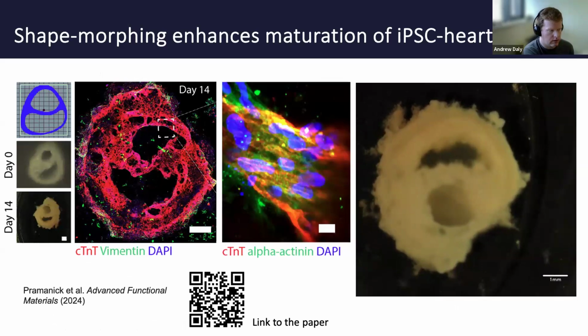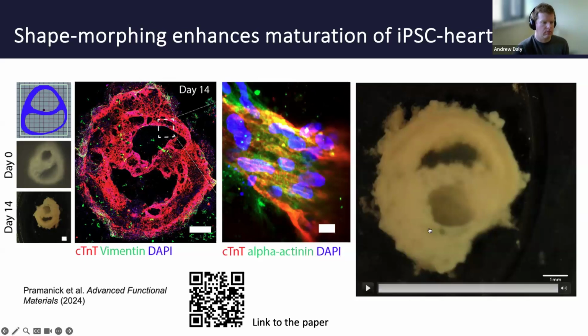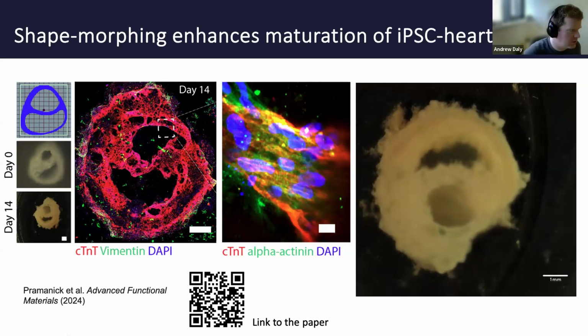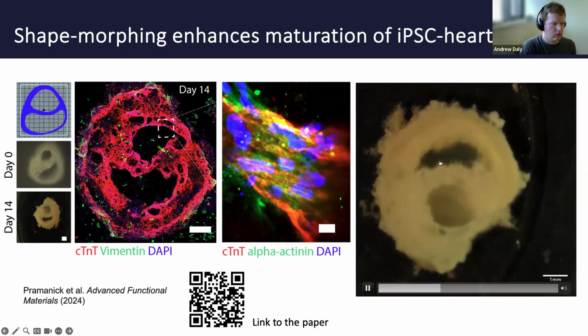Just maybe to finish, this is a scaled up geometry. So looking at a cross section with two structures mimicking a ventricle, that shrunk over 14 days, we can see a lot of nice troponin staining indicating viable cardiomyocytes. We were able to see some cell alignment along the principal tissue axis, although it's obviously not perfect and there's more work to do. And here you can see the contraction of that larger scale tissue. So this is about 7 by 8 millimeters in size. So we're now working to scale this up.